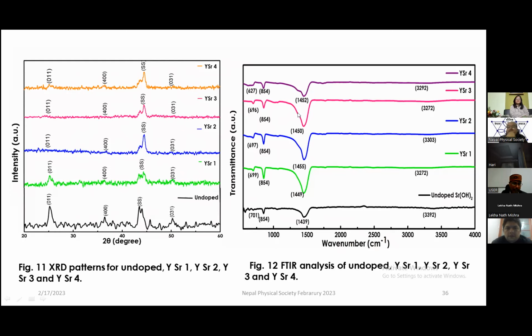One can see that 854 corresponds to carbon contamination, and 1439 corresponds to the water molecule, and the physically absorbed OH bond is there at 3300 to 3800, on the right hand side. So from FTIR we are getting the information that yttrium has been doped here, because the shifting is taking place and it is creating the defects.